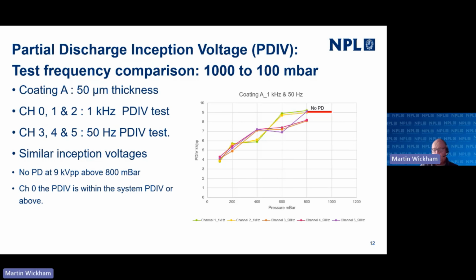However, you can form a corona above the surface of the plastic more easily at a higher frequency. So sometimes we have to test down at 50 hertz, which obviously takes us longer than at 1 kilohertz. However, the inception voltages are not dissimilar, but potentially the failure mode in the coating is, because if you're forming a corona above the plastic, then you may well be damaging the plastic more rapidly than you might otherwise.